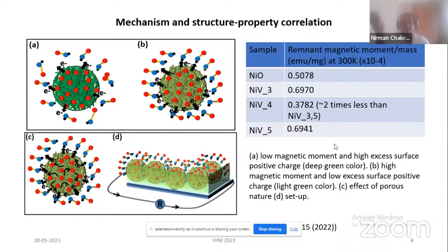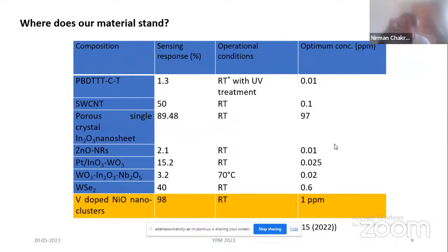So this is one of the very few studies that has been done, which shows that yes, the magnetic property of materials affects the surface behavior of this kind of thing, and this also opens a way for effective room temperature nitric oxide sensors. So if we look at literature, our sample has a very high response of 98% at room temperature towards a very small concentration of gas, that is basically 1 ppm.